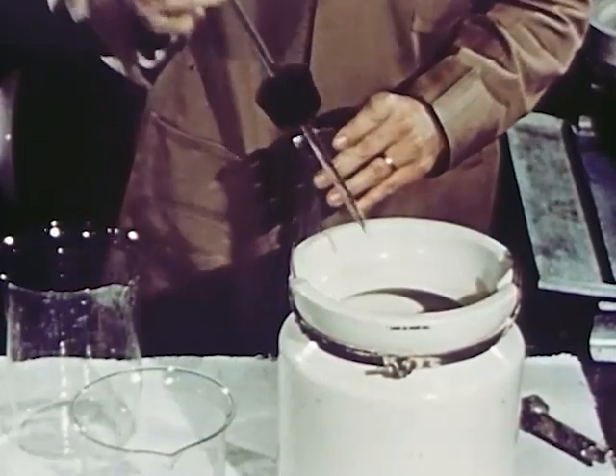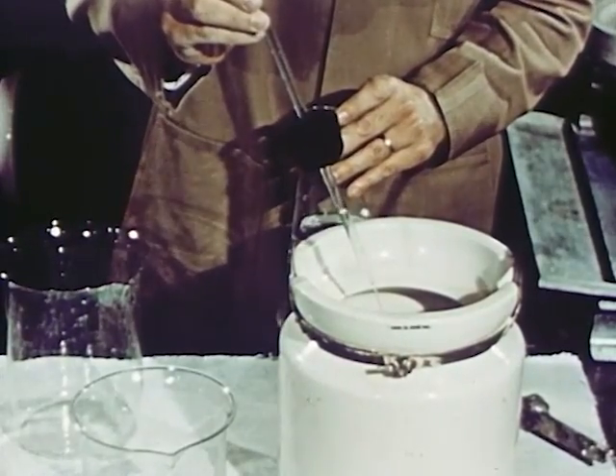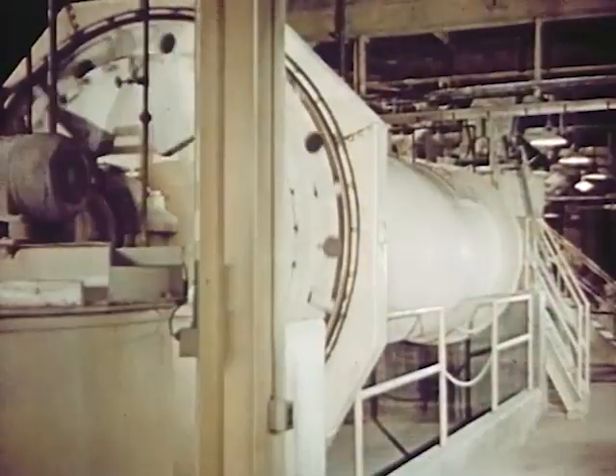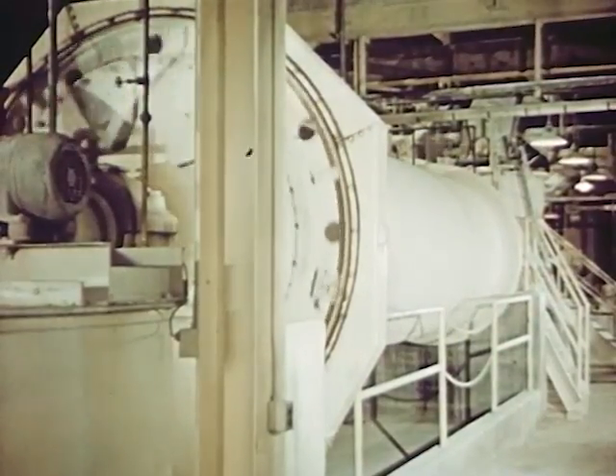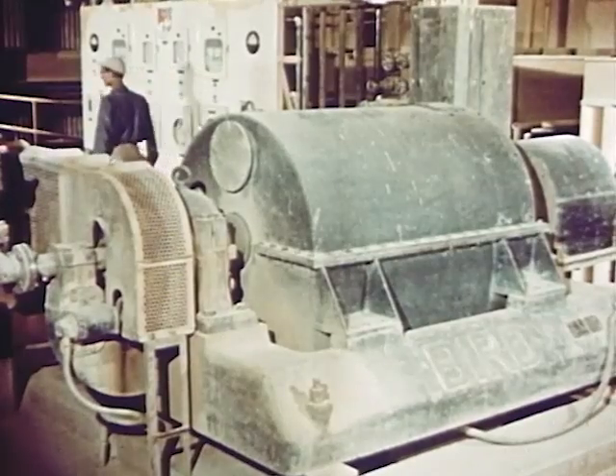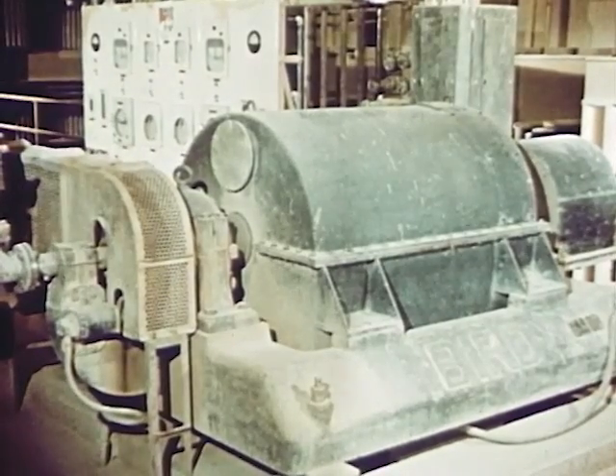After the pigment is suspended in water, dispersing agents are added to the slurry before it is ground in pebble mills in a closed circuit with centrifugal classifiers, which return oversized particles for further grinding while sending on the finer sizes for surface treatment.